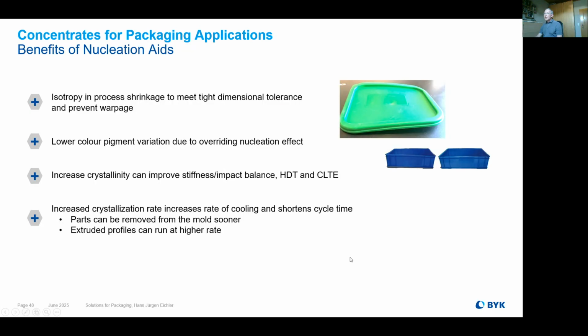So that is the benefits of the nucleation aids, means you can reduce the anisotropic things, so it might reduce also in case of shrinkage, and keep your dimension tolerance and warpage reduced. So effects which are coming with pigments, especially phthalo pigments, are tending to warp. The nucleation effect will help also here from the nucleation agent to overcome these points of the pigments. It will increase the crystallinity and might improve the stiffness and impact, HDT and CLTE, and of course the cycle time is reduced, and that means you get more parts out of the mold and you can form it out quite soon.